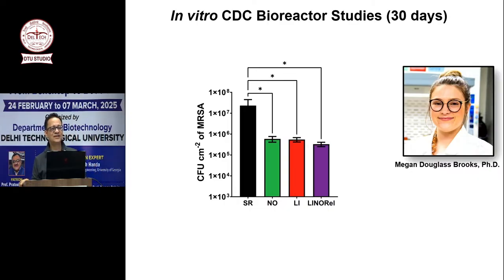We got some clinical strains of different bacteria from CDC. I'm just showing one here, but she tested like 6-7 strains of bacteria. Because we had a grant from CDC, they wanted 30-day studies with all those strains for us to show that our material works. These were very difficult studies because it was a 30-day bioreactor. Bacteria was growing like crazy sometimes, so she had to repeat some studies because of contamination issues, but basically we showed that we were doing very well with our material.